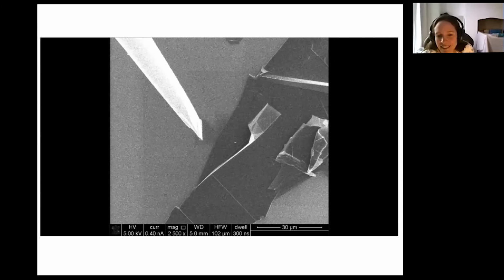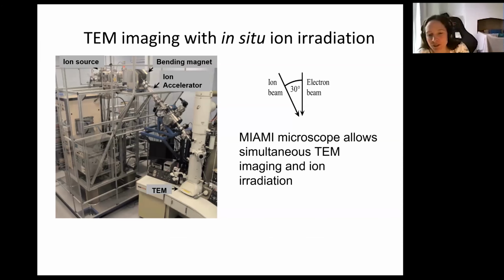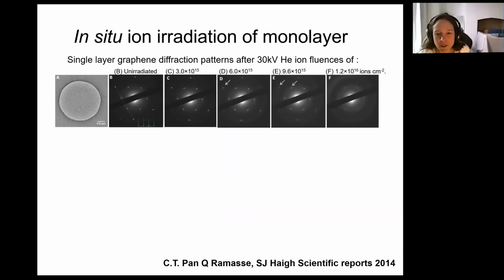Okay, so to understand this and lots of other types of deformation, I want to go back to some work that we did in collaboration with Steve Donnelly and Jonathan Hinks at the University of Huddersfield, using what is confusingly called the MIAMI microscope. It's not in Miami, it's in Huddersfield, which is rather disappointing when you send a student. You send them to the MIAMI microscope and they only have to drive half an hour into the Peak District. But this instrument is very special because it's able to both perform ion irradiation of the specimen while simultaneously imaging it in the transmission electron microscope.